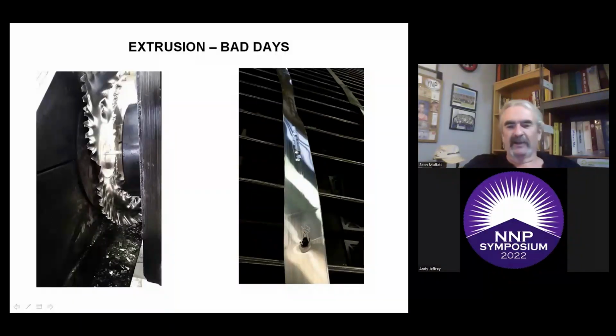Now, depending on what the chunk of stuff is that came out of melting, if it's a piece of silicon carbide refractory material, or mud as they call it, it can actually damage the die, and then that will just leave a big line or a strip or something all the way down your strips, and so you just waste that entire strip. Has to be melted. And if you don't waste it and you go ahead and send it through the process, that line or whatever the defect is can show up on your finished coins.